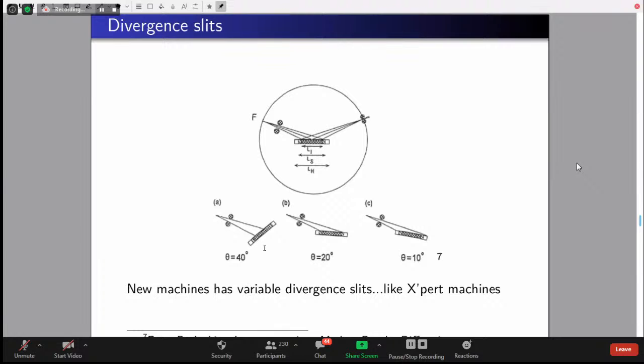So here, whatever you are seeing, these gray dashed lines are the area of your material. The rest is your sample holder. At a particular angle of theta, which is 40 degrees, we are seeing only the material. But when it decreases to 20 and further decreases to 10, we are seeing the sample holder also.